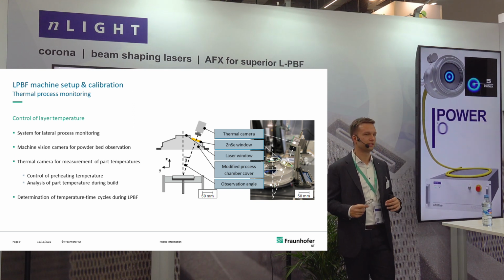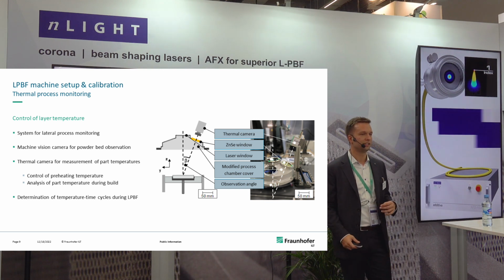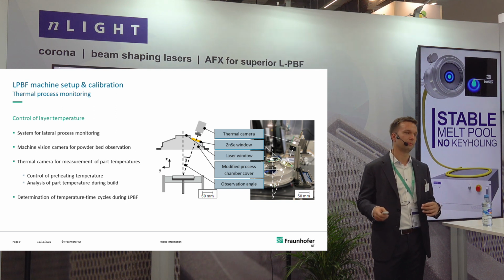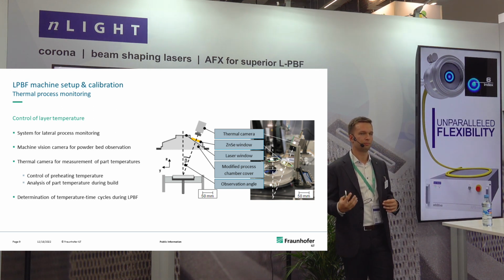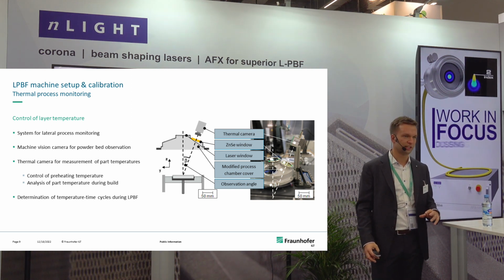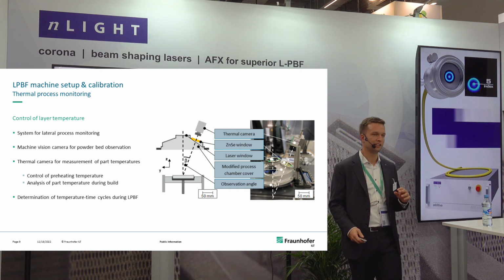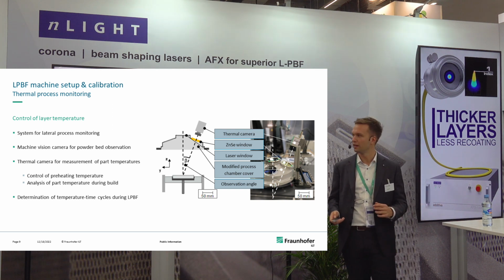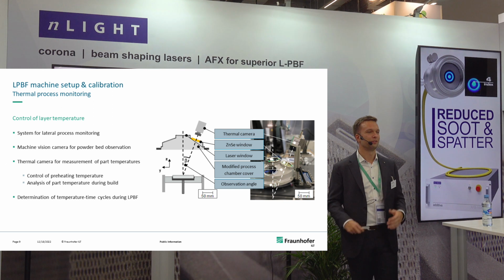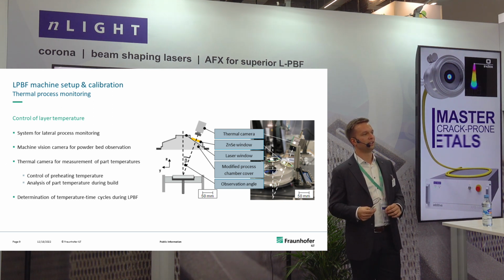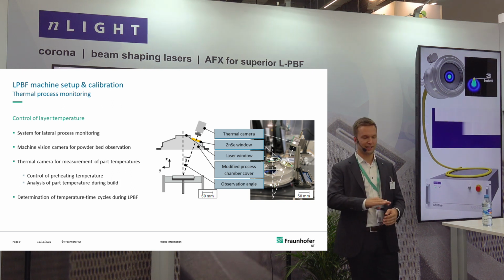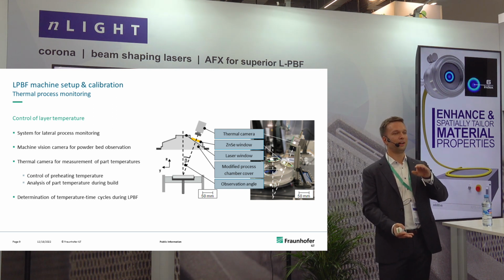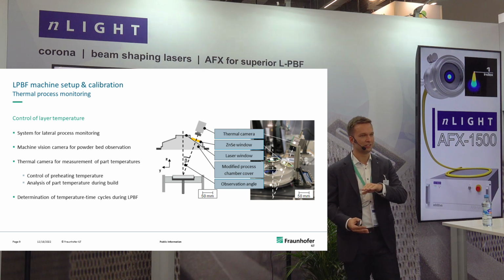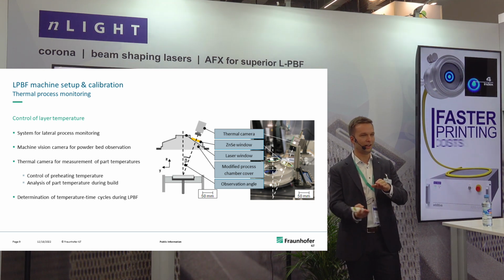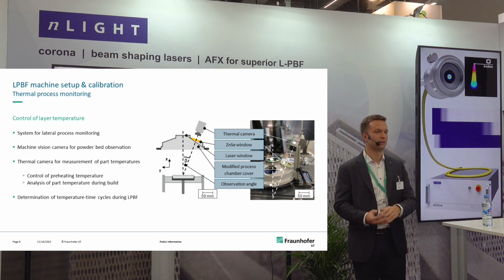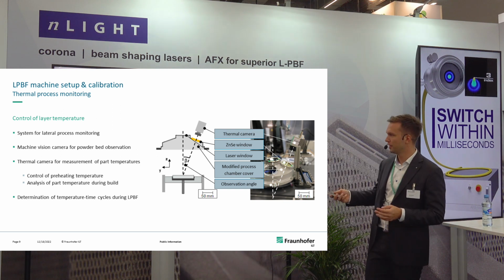Additionally, we also have our monitoring systems installed. We have a modified chamber cover that we can equip with a thermal camera, but also a process camera to observe the L-PBF process, to control the actual layer temperatures over the build, to see if we have some kind of overheating or if the preheating system is actually delivering the temperature we are setting it to. This is quite useful if you want to maintain homogeneous processing conditions. If you imagine building up a larger component and you just set the base plate temperature constant and build the part, most likely the temperature in the active layer that you're currently processing will change because the distance between our heat source, which is the plate, and the active layer becomes larger and larger, and you have to think about measures to compensate these losses.